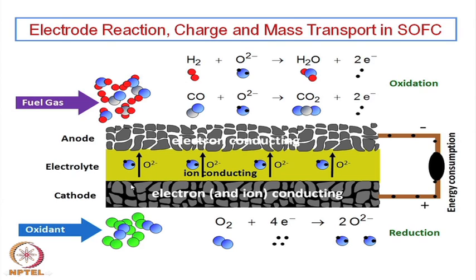Because there will be a potential difference, there will be high oxygen potential on this side and a low oxygen potential on the other side because the fuel has a reducing condition, low oxygen potential. So, there is a kind of tendency of driving force. In fact, the driving force will be there for the oxygen to move from the higher oxygen potential on this side to the lower oxygen potential on that side. So, oxygen ion will move through the bulk of the electrolyte. Now, this can move because this electrolyte has been chosen in such a way that it has a very high oxygen ion conductivity. There is no electronic conductivity in this.